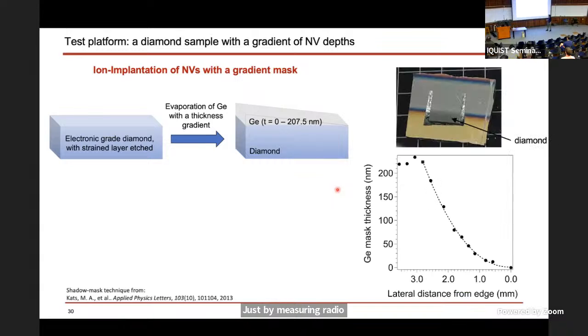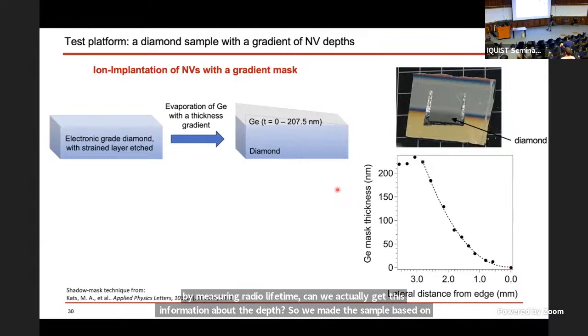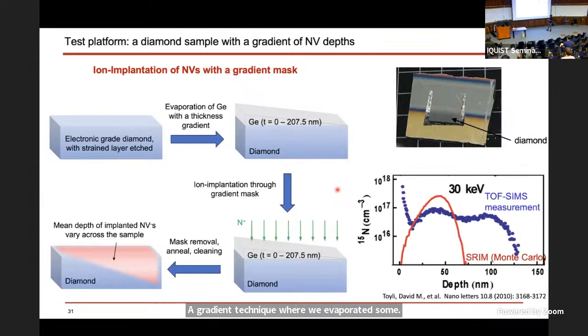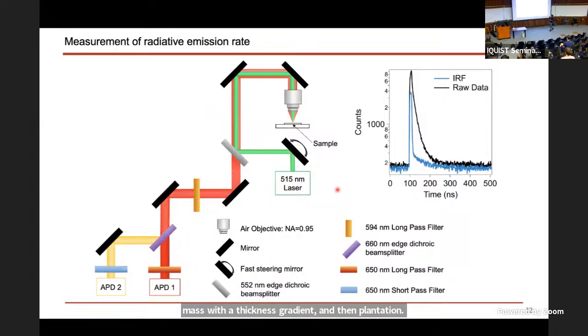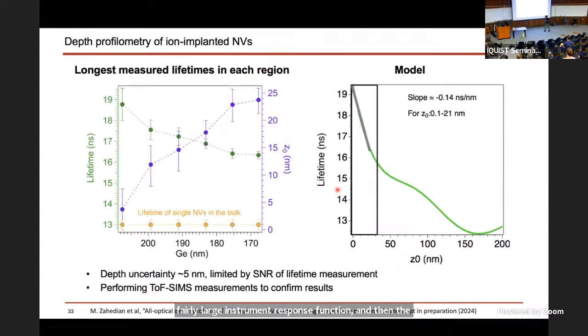So we made the sample based on a gradient implantation technique, where we evaporated some implantation mask with a thickness gradient and then did ion implantation. Then we did lifetime measurements by sending in pulsed green excitation and collecting red fluorescence in a time-gated way. We actually have a fairly slow laser, so we have a fairly large instrument response function, and the black curve you see is the raw lifetime decay. And so this is our result.